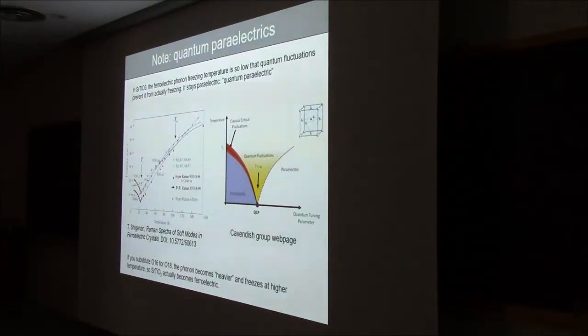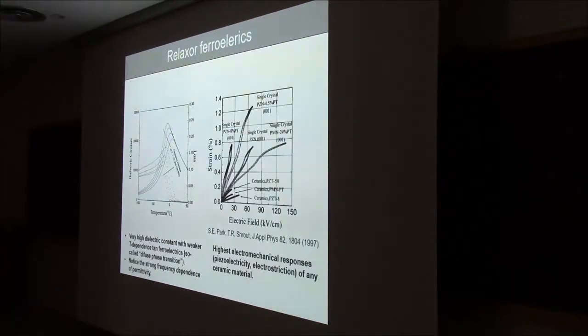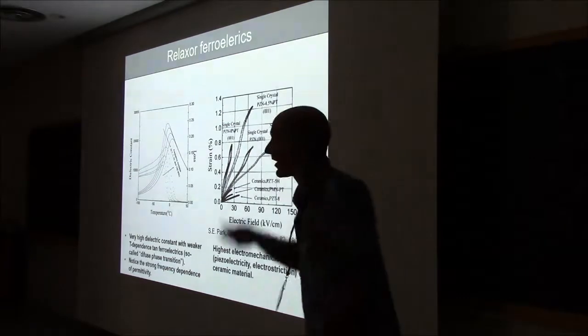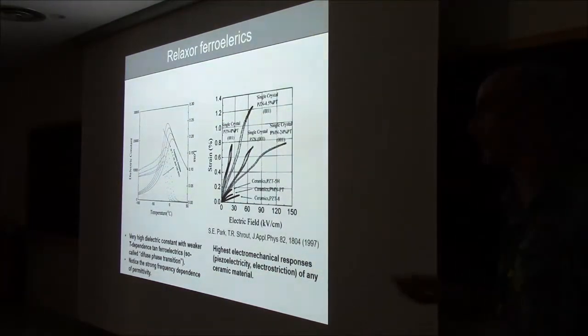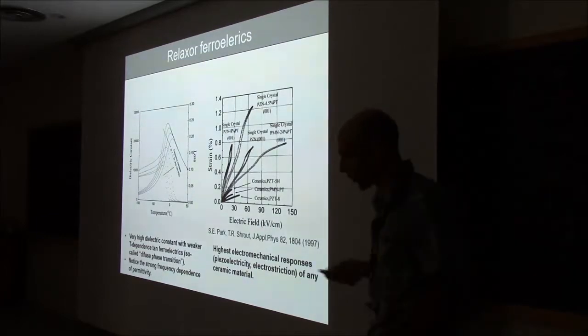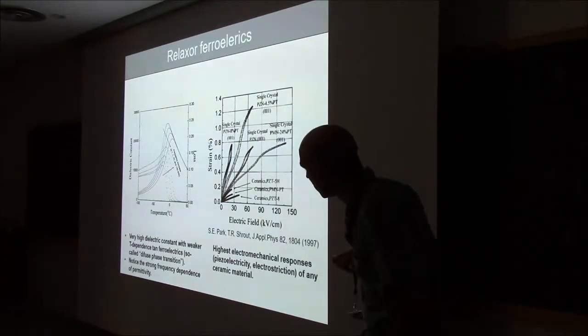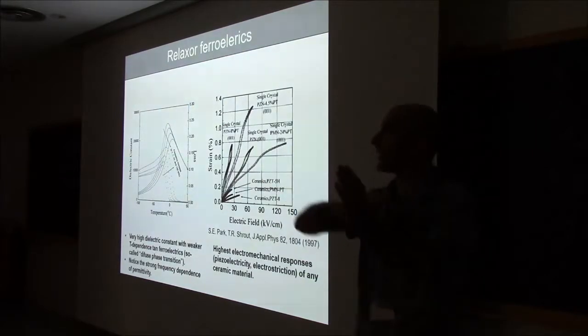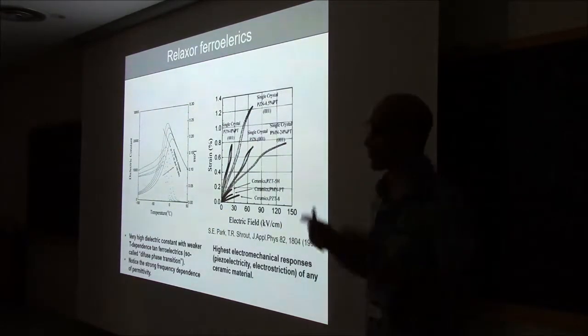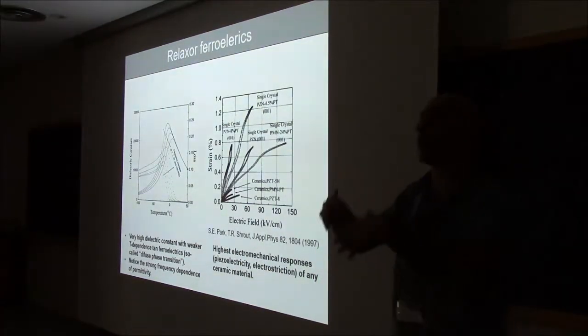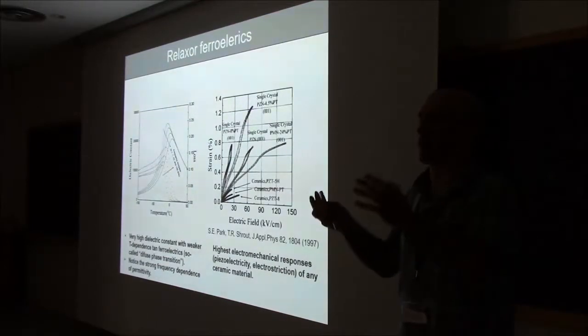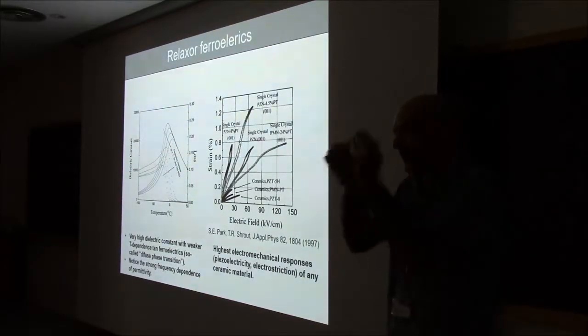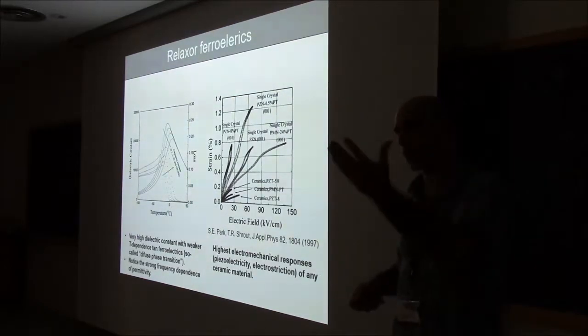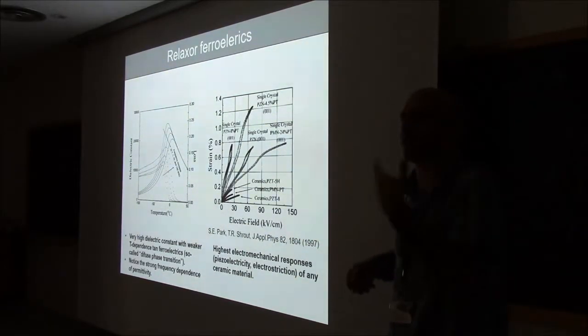Okay, so quantum paraelectrics, of which STO is the most famous example, is one family of almost ferroelectric materials. Relaxor ferroelectrics is another family of, let's say, almost ferroelectric materials. And I say almost ferroelectric because at low temperatures, where your material would normally have a spontaneous dipole moment that is ordered over a long range, in the case of relaxors, this ordering happens over a very short range. So you have clusters or domains. Physicists will be arguing until I die about what's the true exact nature of a relaxor ferroelectric.